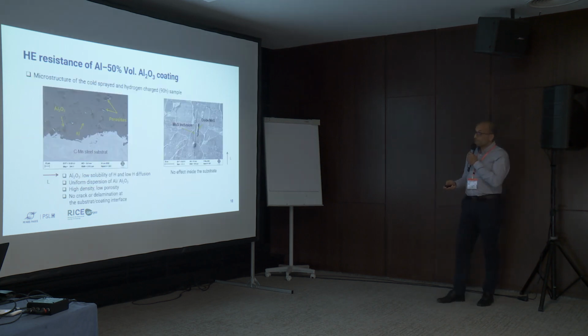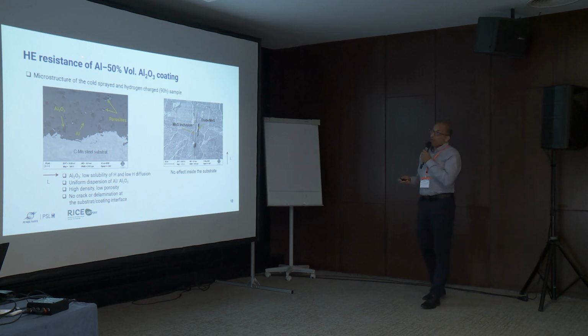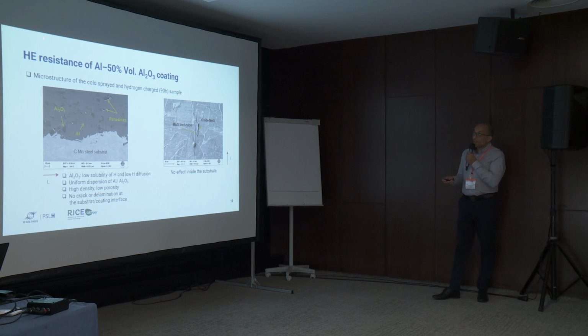Here you can see the coating, a composite coating with 50% in volume of alumina. This alumina was chosen because of its low solubility of hydrogen and its low hydrogen diffusion.